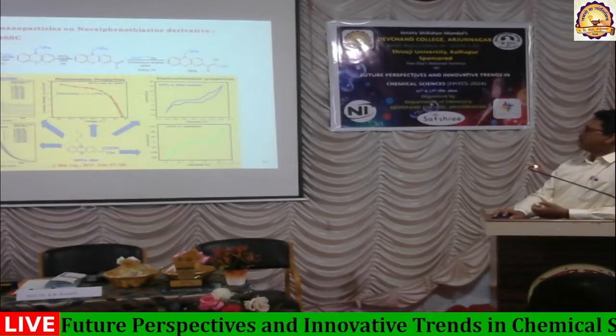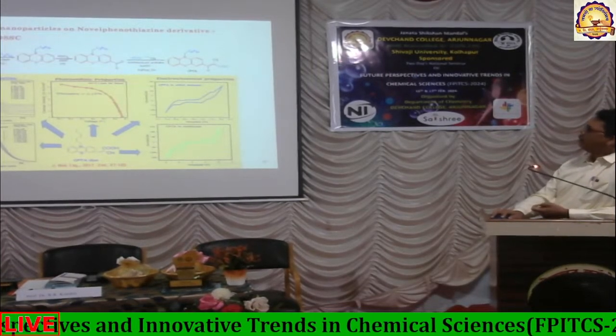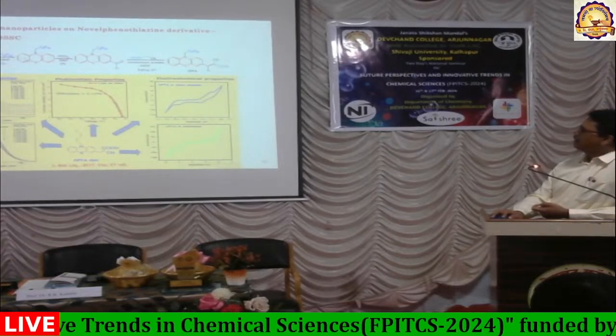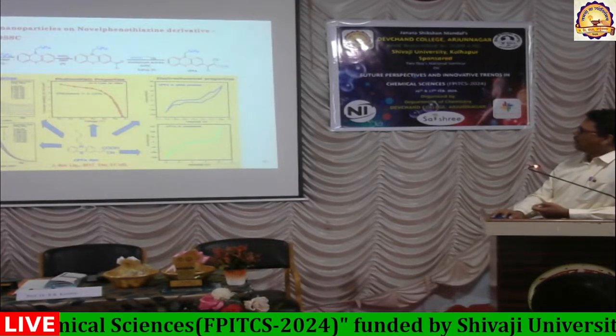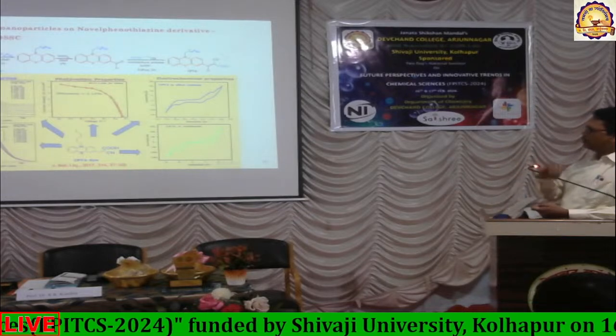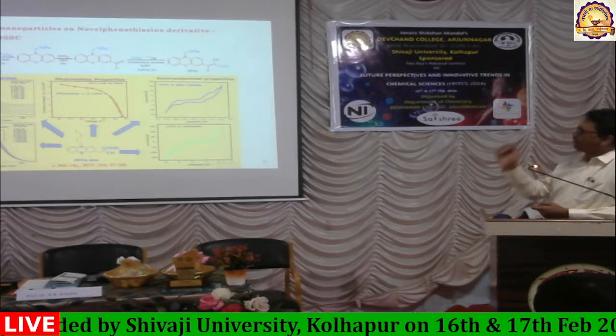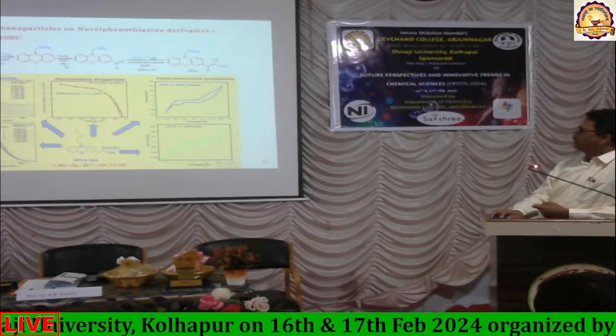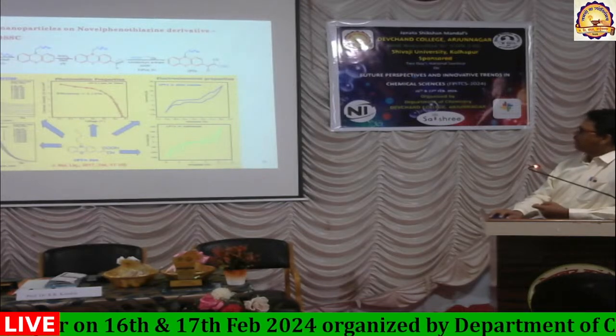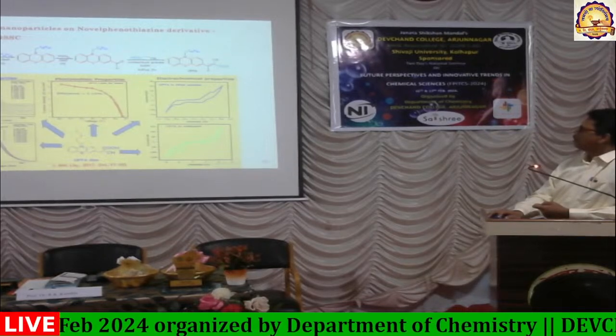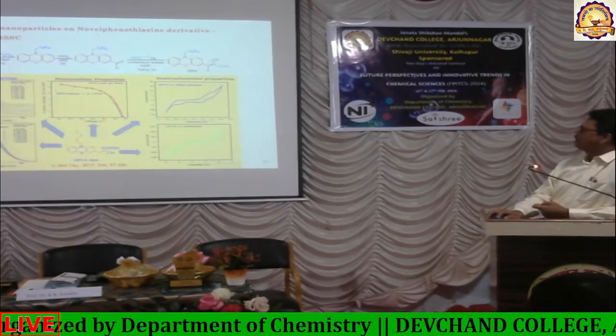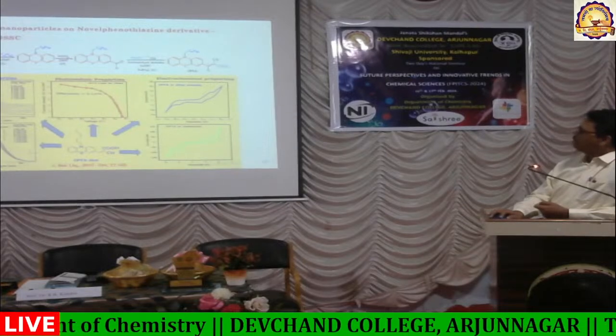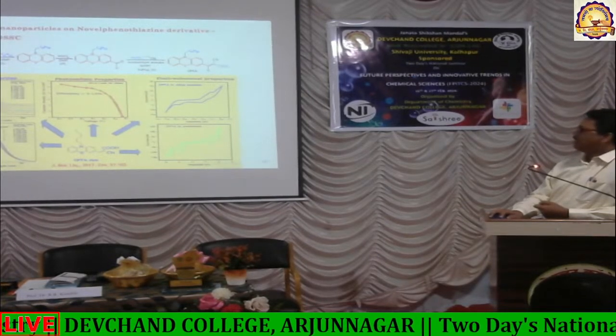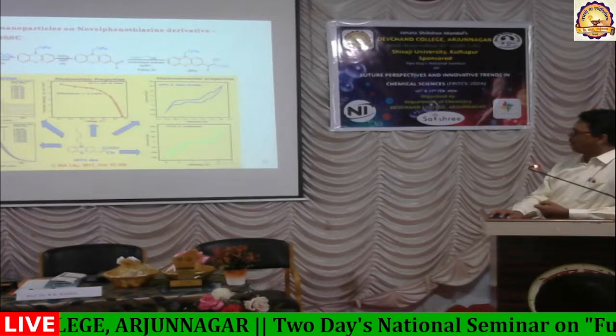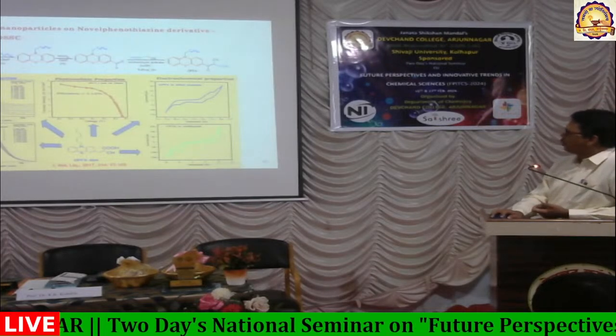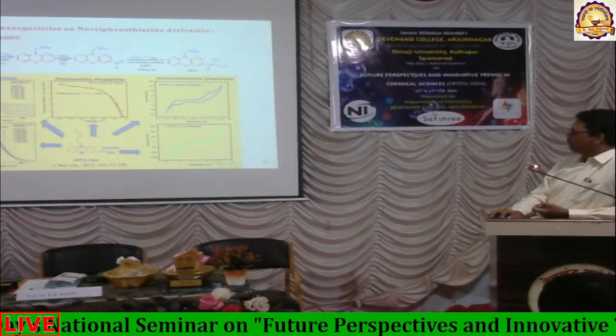So here, this is the work done by me in the US, where we used this phenothiazine, and we introduced a large alkyl moiety here, to reduce the agglomeration of the dye on the semiconductor. And then by the Vilsmeier-Haack strategy, we introduced an aldehyde over here, and then we introduced a linker group which will link on the semiconductor, that is TiO2. And then these spectra indicate the UV and the fluorescence spectra of the compound, which is in the region of more than 600, almost like 600.